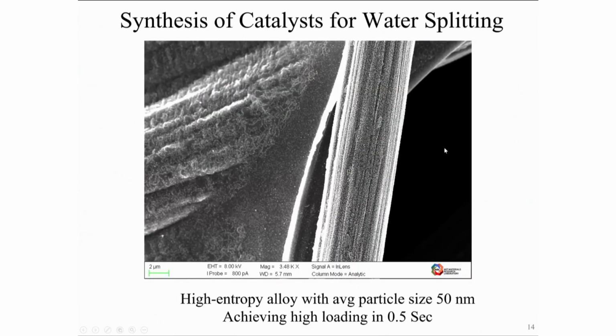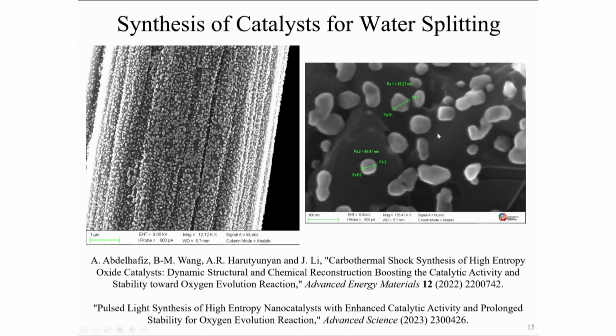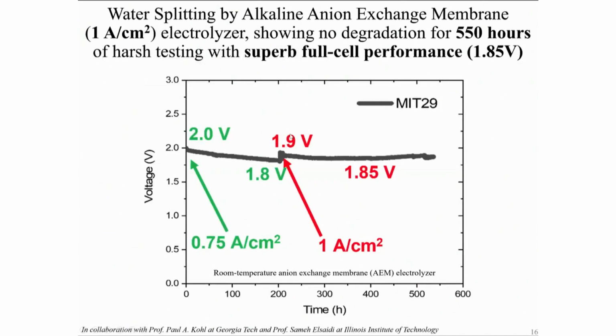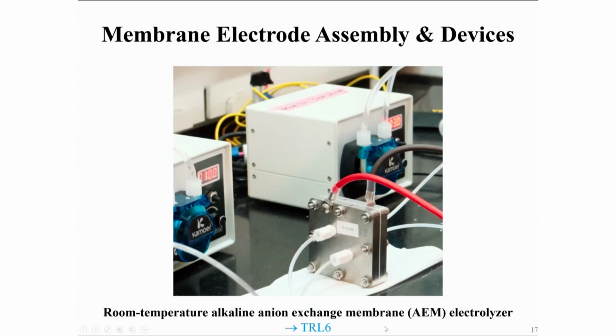So with this approach, we have developed new catalysts for water splitting. So these are multi-metallic catalysts. However, once we put them into water, they turn into high entropy metal hydroxides, oxyhydroxides. But the upshot is we're able to, in collaboration with Professor Paul Kohl at Georgia Tech, develop these high performance anion exchange membrane electrolyzers at an industrial current density of 1 ampere per centimeter squared and a pretty low voltage of 1.8 volts for now more than 1,000 hours. And so this is something we are trying to push to higher TRL level at the membrane electrode assembly and device level.